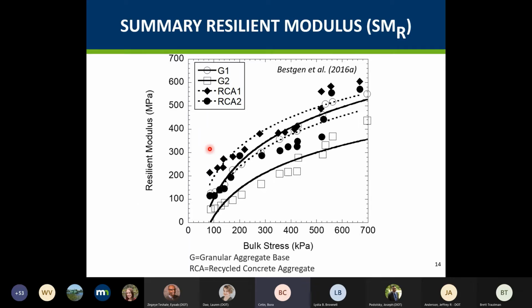So this is one of the graphs that I took from one of my previous studies that shows on the y-axis the resilient modulus values versus the corresponding bulk stress values. As you can see, and as the majority of you know, I believe, resilient modulus most of the time shows a nonlinear behavior, and it is stress dependent. So depending on the bulk stresses that your aggregate materials are exposed to during this resilient modulus test, and G represents granular aggregate base and RCA represents recycled aggregate.